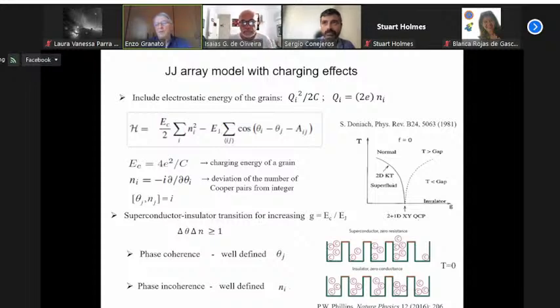Now, the easy way to think in terms of the experiment in this model is that as you make the film thinner, the amount of superconductivity decreases, the number of connections decreases, and therefore the Josephson coupling decreases. As it decreases, the ratio increases. Because the charging energy is always there, but if it's too small, then you're still in the superconducting phase. But if the superconducting part actually decreases, then eventually the other one dominates. One competes with the other.